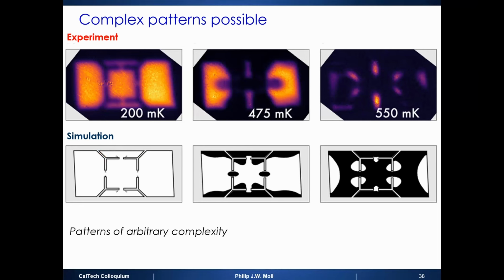So what you could do to achieve this is now to add more slits into this. Nothing crazy happens. All that the slits do is they change your mechanical boundary conditions. As you change your mechanical boundary conditions, you change the strain field. As you change the strain field, you change the TC landscape. And so what we've developed is essentially a COMSOL-based simulation, very simple, of how TC should look given a certain pattern of slits. And what we now are working on is the inverse, that we could say, I want this pattern of TC. Please tell me how to slice this up.